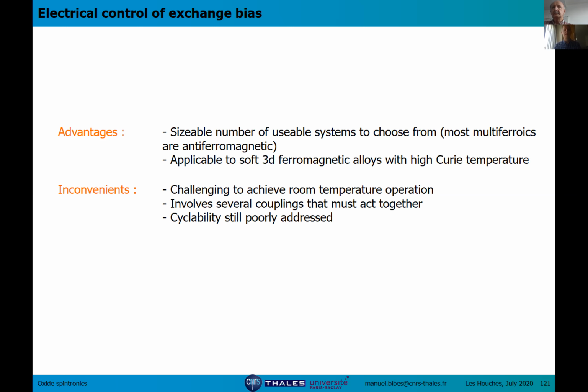cobalt iron. And it's a quite complicated mechanism because you have all these different couplings that act together, coupling between the electric field and the polarization, between the polarization and the spins in the multiferroic, and between the spins and the magnetization in the ferromagnet. And all these must act together, and many, many times if you want to make it a device. So this is very challenging, but probably the most promising direction yet.